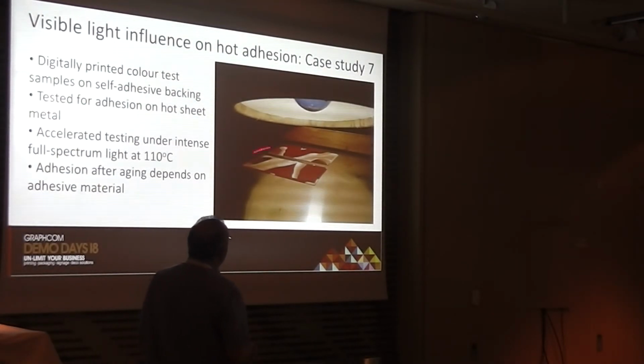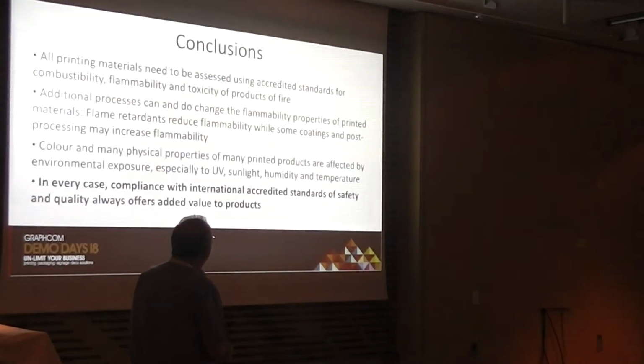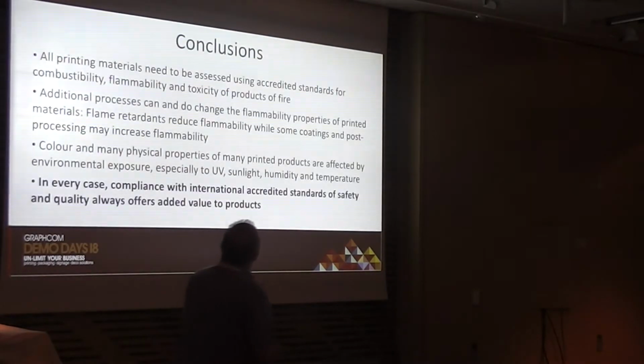And there was another test, of a printed material which was self-adhesive on a steel surface. It was exposed to the sun, and we measured that the temperature of the surface of the steel went up to 110 degrees. So we were doing aging of the colors as well as the material itself and the adhesive. It was quite an interesting little test. We didn't do the full gamut of material testing on this. This is equivalent to sunlight, and we did accelerated testing over a few days only to find out if the adhesive was going to work.